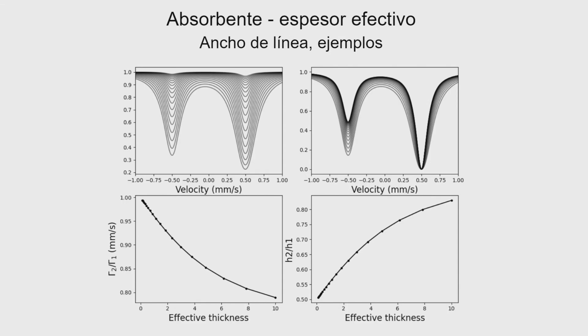So in the low effective thickness, where you don't have saturation effects, you will see a double absorption relative to the first line. But if you have a thick absorber with much more sample, because you make a thick absorber, or because your sample has that absorber, maybe you will read something different. So here your result says that you have double the amount of iron in this line than in this line. If you don't care about effective thickness, you maybe can say that you have almost the same in both lines. So it's there to take into account.